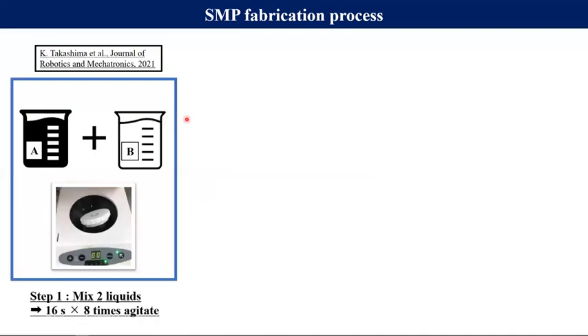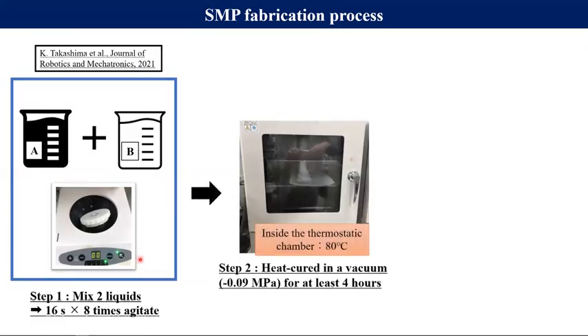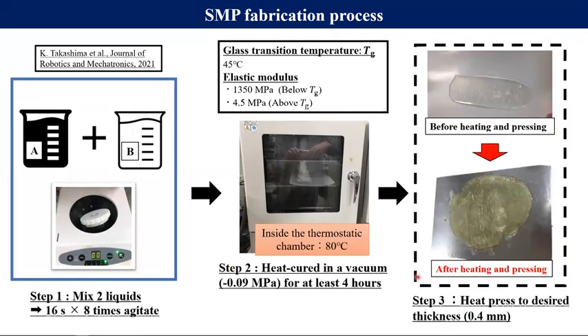So here's the SMP fabrication process. First, liquid A and B were stirred in the following cycle using the machine shown here. And after that, the stirred SMP was heated and cured in a vacuum for at least 4 hours. And finally, the cured SMP was heated and pressed to the desired thickness. That was 0.4 millimeter this time. And the catalog values of SMP are here.